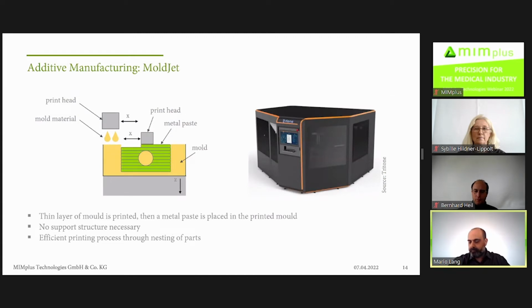The next process to make the AM green part is the mold jet process. In this process, you print a wax-based mold and you fill the mold layer by layer with a metal paste. And so you have a better surface quality than in the other process. And you have as well no support structure necessary because you have a mold out of a wax-based mold. And this process is quite efficient for a high number of parts.